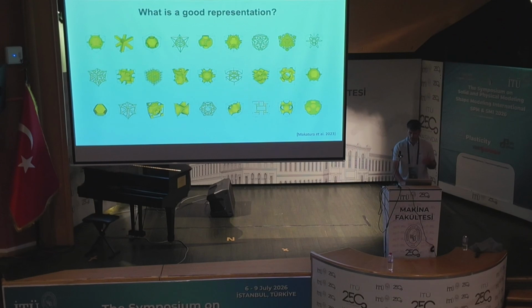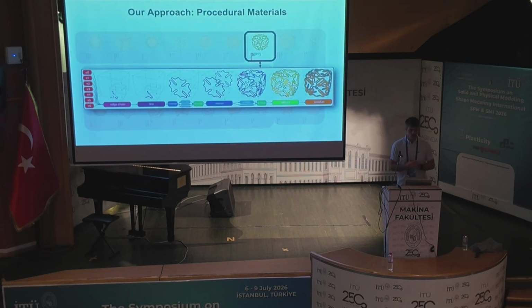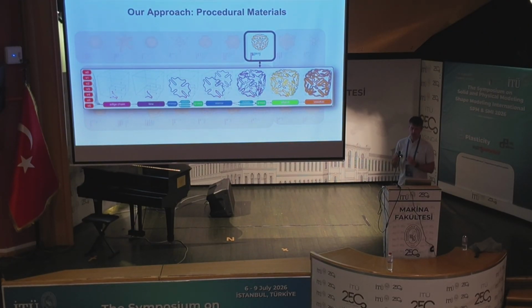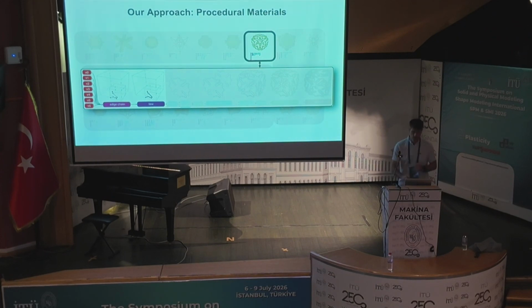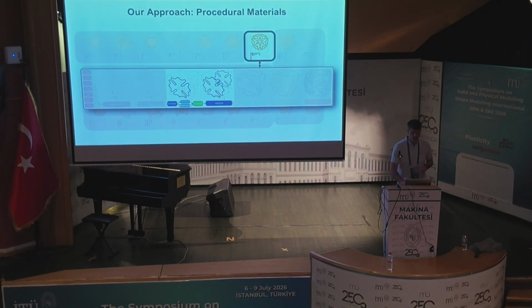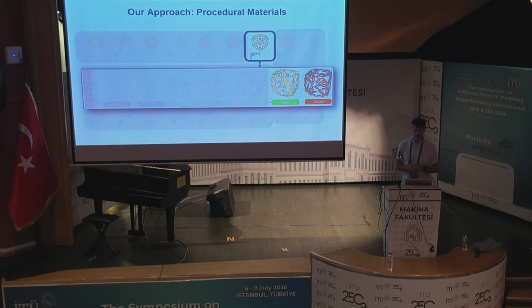So to address this problem, we came up with a procedural approach. The idea is that we came up with a graph-based representation and combined this with a new user-friendly interface that allows researchers to quickly model cellular metamaterial structures. It allows you to build metamaterials by composing various building blocks together in a quick way. So at a high level, our approach uses a set of operation nodes to first define small skeletal pieces of the target structure, then apply a series of transformations like mirroring or rotations to fill the unit cell, and then apply thickening or other geometry processing operations to finally generate a physically realizable structure.